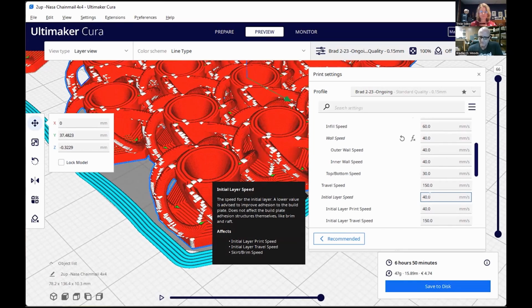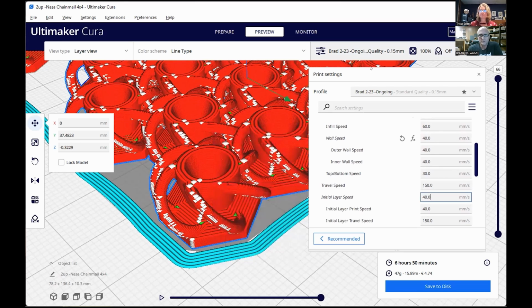But the most common problem that people have with our material is that on their first layer, they'll have the nozzle too close to the bed. So the bed is literally clogging the nozzle. It can look like a filament clog in the nozzle, but it's actually the nozzle being too close to the print bed. Exactly. The bed is preventing the material from flowing through the nozzle.